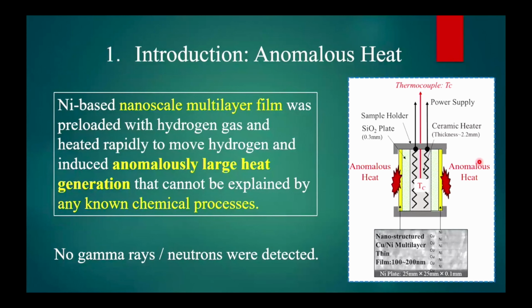Our experimental method: we use a nickel-based nanoscale multilayer thin film like this. This one was preloaded with hydrogen gas and heated rapidly. Absorbed hydrogen moved toward the vacuum surface. And at that time, we observed enormously large heat generation that cannot be explained by any known chemical reactions. That's our experimental method. And during this process, we could not detect any gamma rays or neutrons.